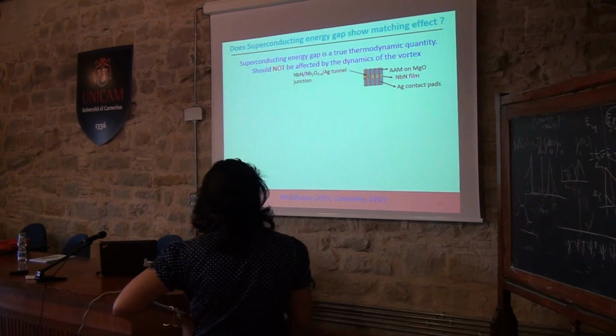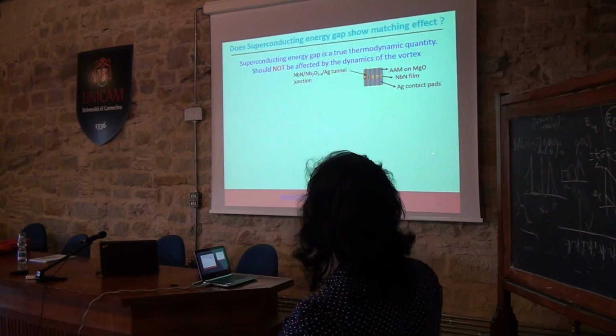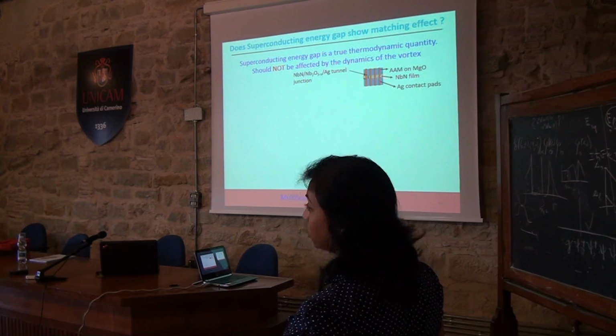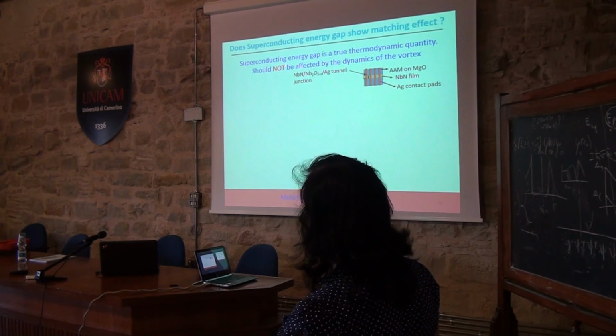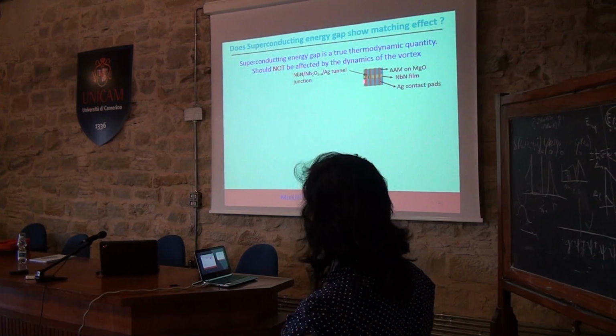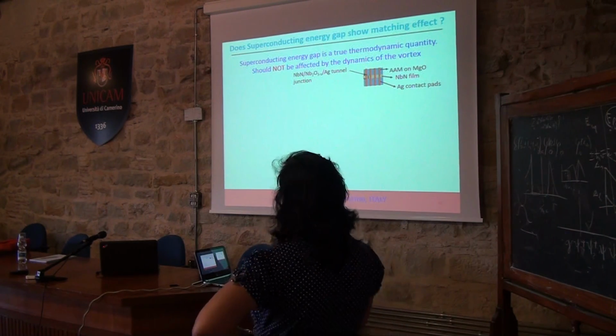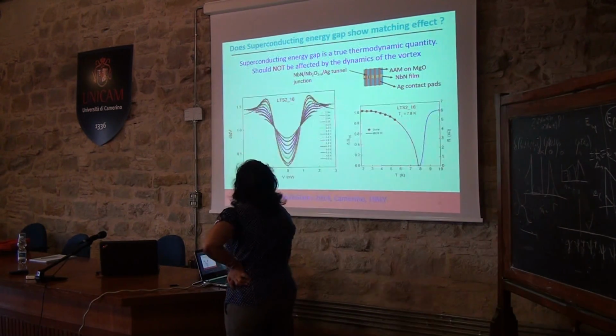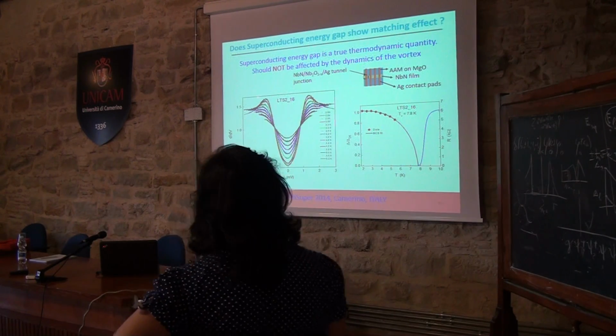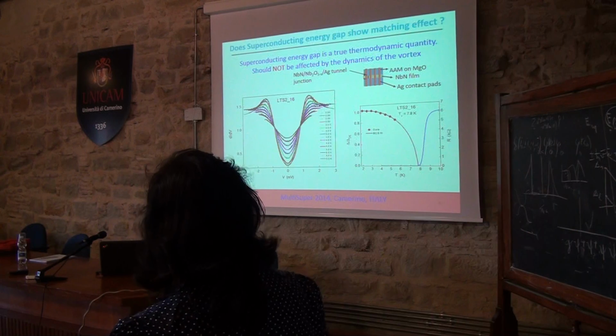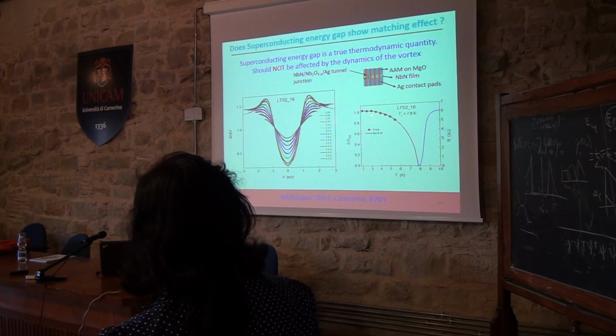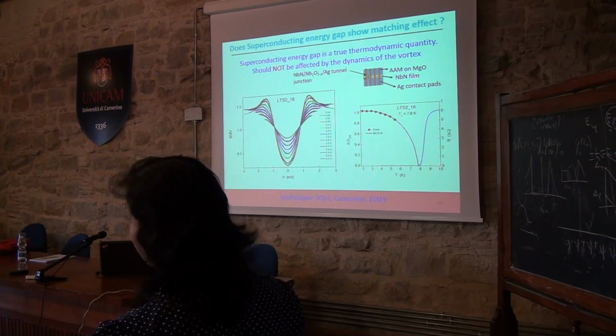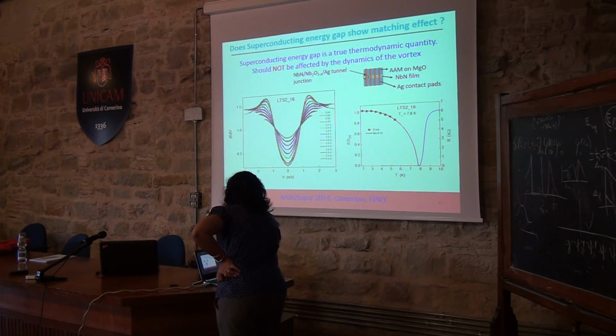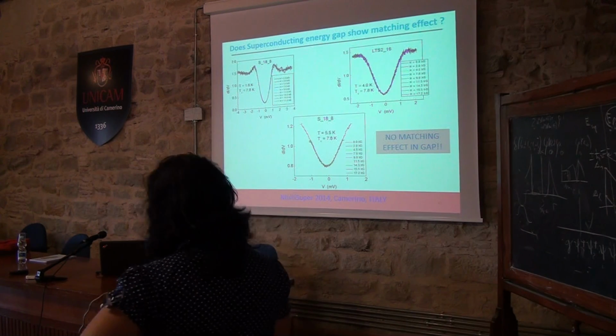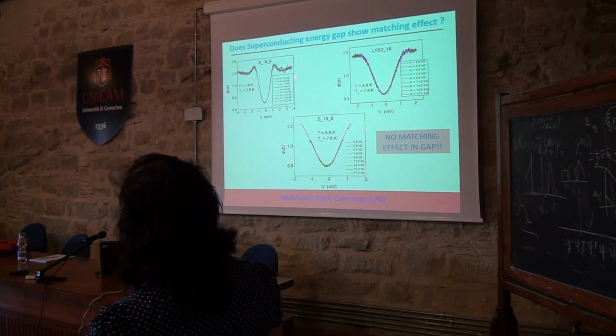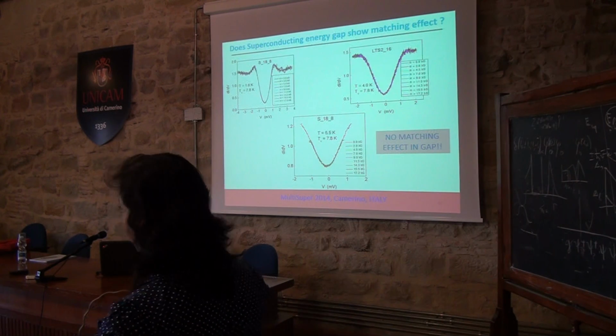For this we prepared tunnel junctions on our template. So you have this niobium nitride film which was deposited on the template, and then we oxidized it, and then a silver top electrode to form the tunnel junctions. We saw whether this is giving the proper conductance spectra, as a function of temperature, which we did on our system. This behaves like a nice BCS superconductor. And now we measured the tunneling conductance as a function of magnetic field, to look for the matching effect.